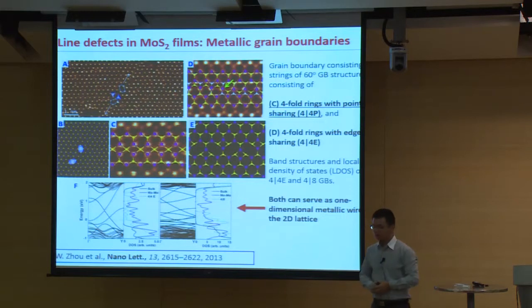Okay. There's one thing very interesting is that if the rotation angle between different domains is 60 degrees, like I'm showing here, 60 degree grain boundaries, this line actually from the calculation is metallic. So this is the only case of metallic grain boundaries in molybdenum sulfide.